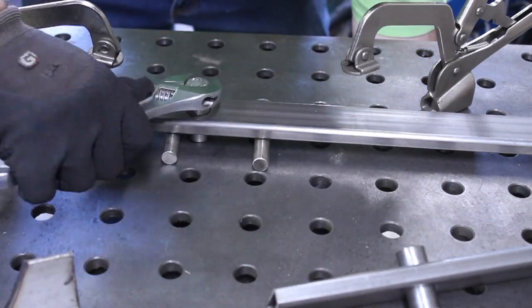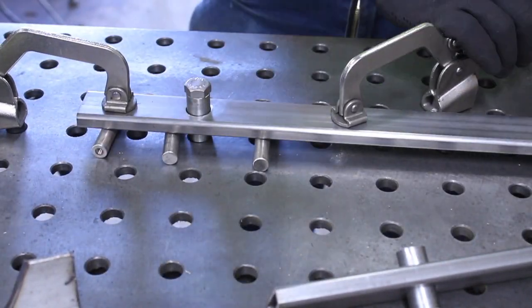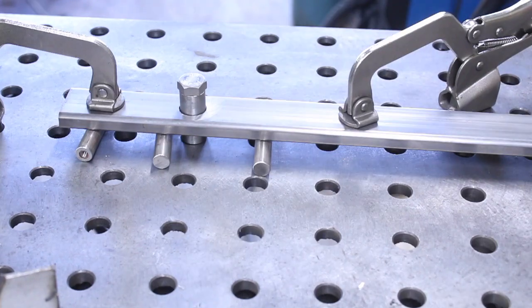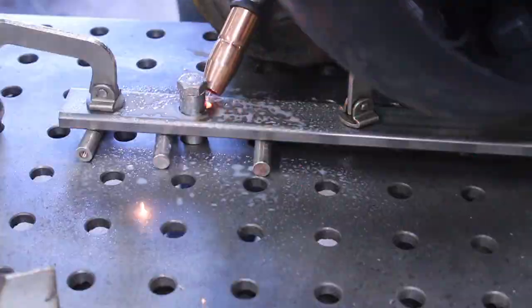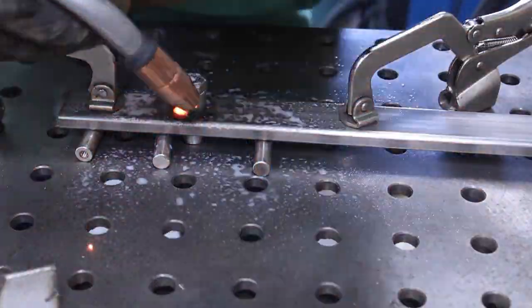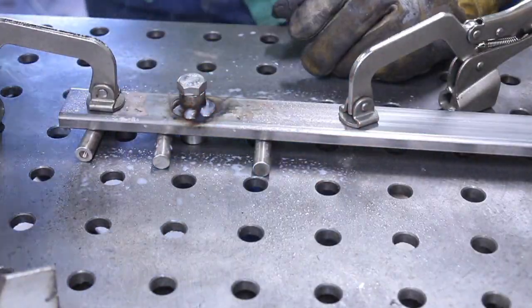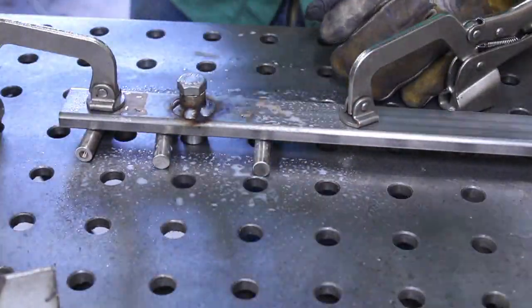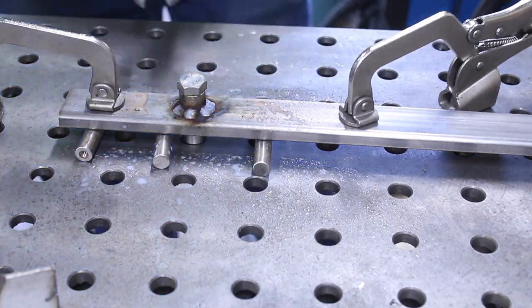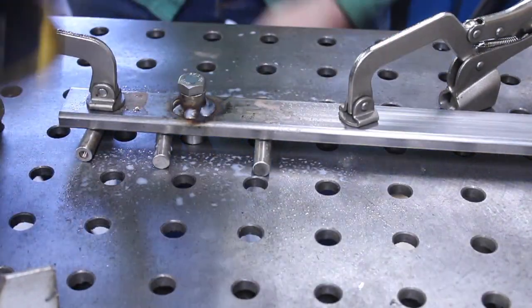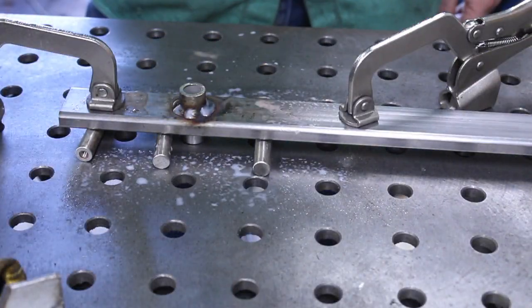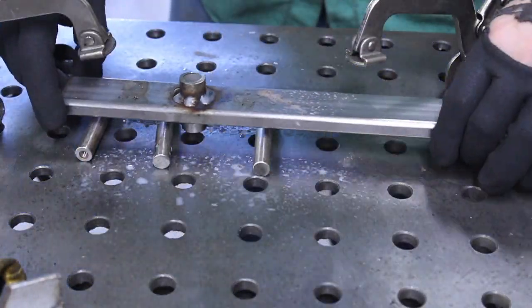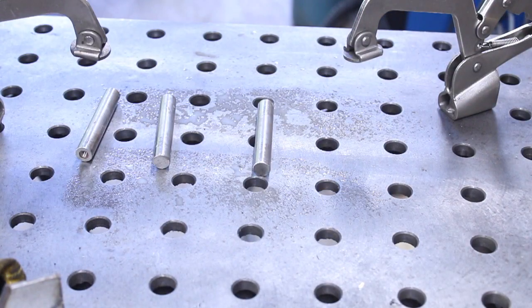Here's where the fixture table really earns its keep in keeping everything straight, because stainless steel, again, with the chromium content in it, is an extremely poor conductor of heat, so the warping is very, very bad. So you really have to baby it in terms of keeping it straight when you're putting this level of amperage and heat into it. You can see how it's really belt and suspenders construction here in terms of fixturing, where anything I can tie down, I am tying down, because you don't want it to warp. Once you've warped, you really throw away the part.